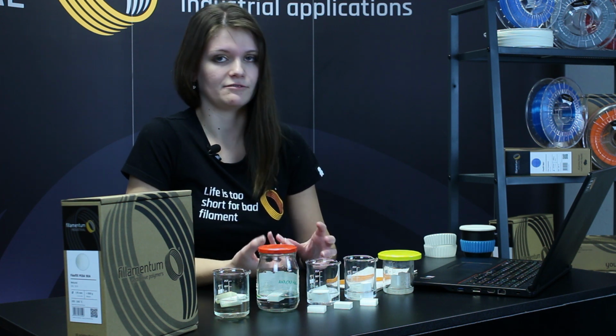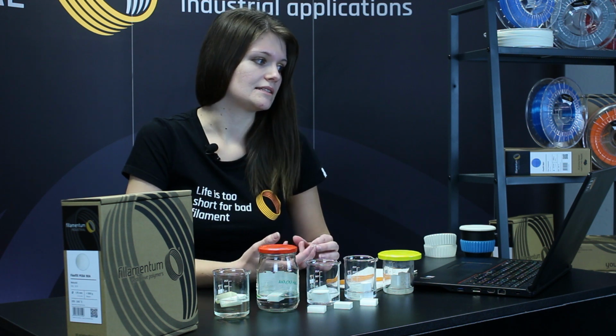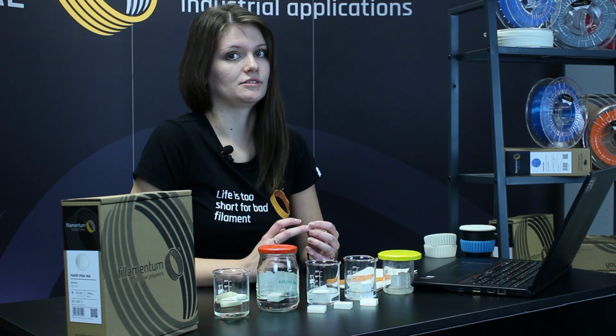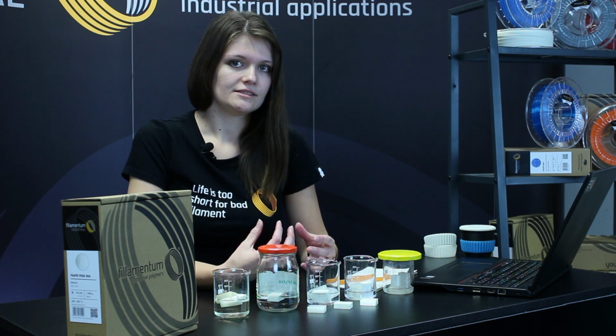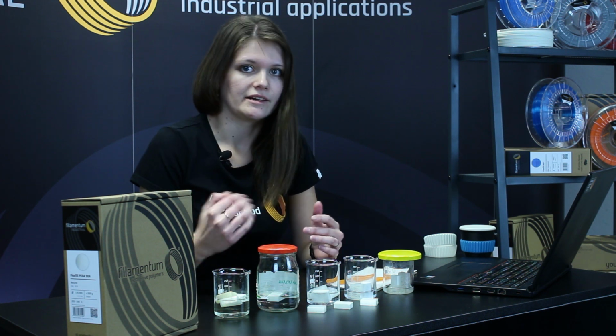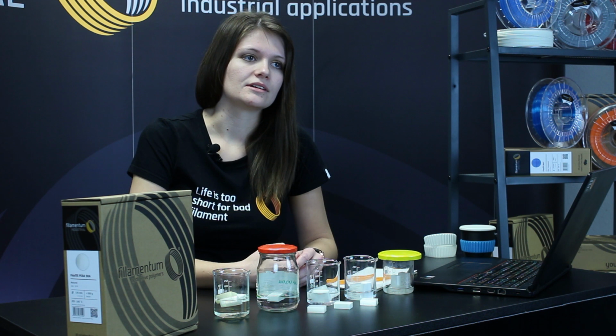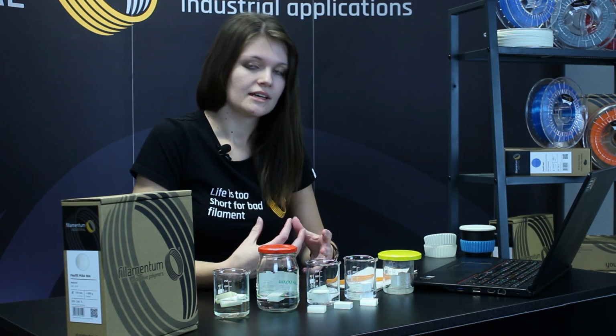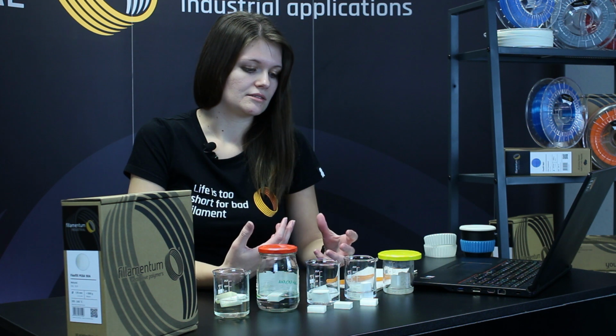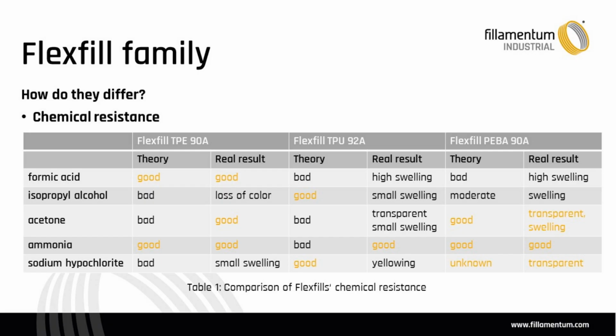our test has shown something different, because it is also dependent on the 3D printing technology. Due to the layers that are connected layer by layer, it can have a higher influence on the printed object than it is in bulk, for example, made by injection molding. Then we can have a look, for example, in case of TPU and isopropyl alcohol, that the TPU is theoretically resistant to IPA, but in case of a 3D printed object we can see little swelling, and it changes its dimensions.